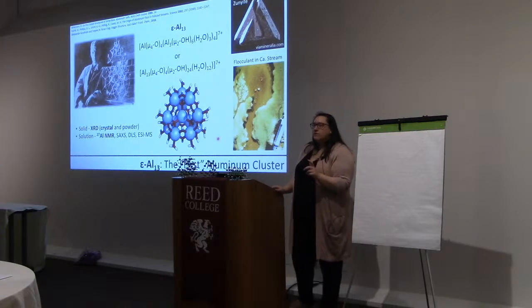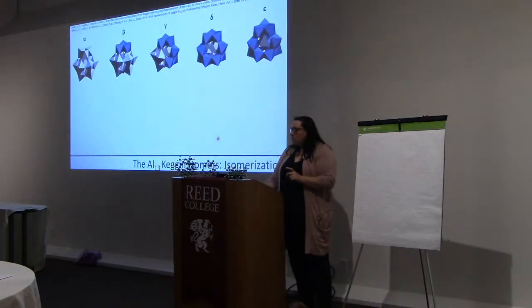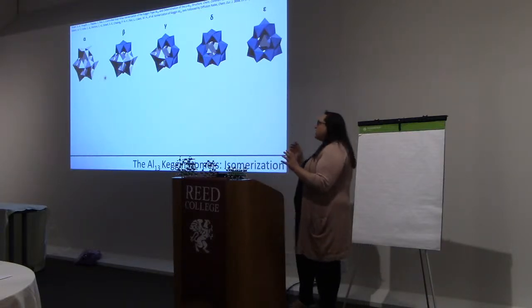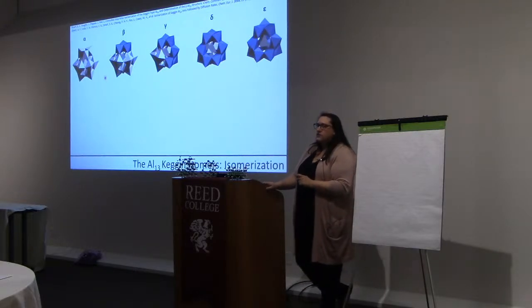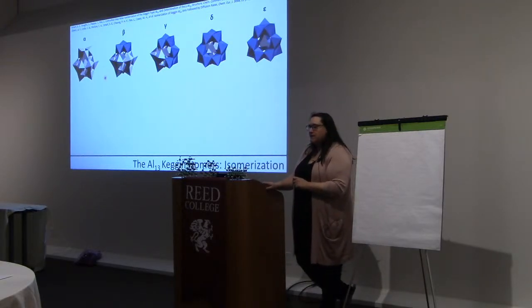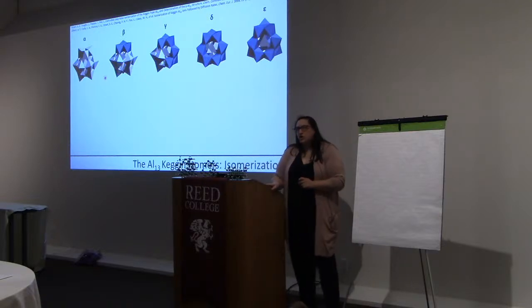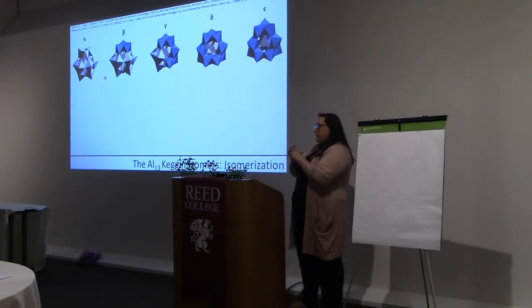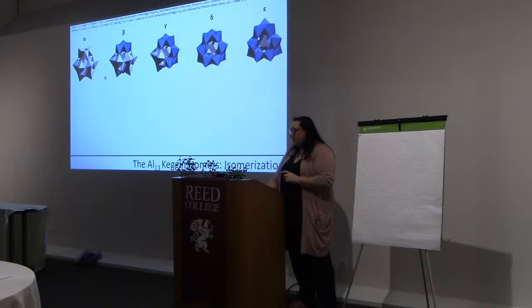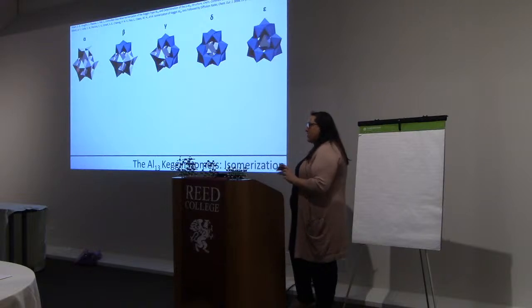The reason I say they're very similar is because we have isomers, and the unit in zunyite is actually the epsilon isomer. So the alpha isomer is the one that was first discovered with tungsten, because tungsten is larger than aluminum. Aluminum 3+ is a very small ion, and so they can sit closer together and you get this epsilon instead of where the metals sit a little farther apart in the alpha. Now the difference between these is a rotation of the trimeric caps.